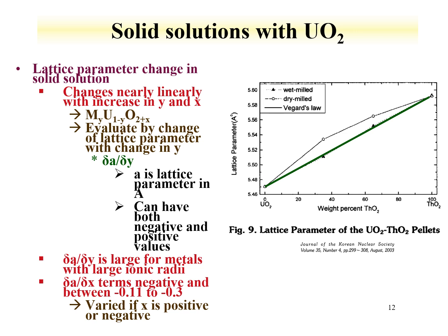So for something that's 50%, the lattice parameter would be a contribution of 50% of the uranium dioxide and 50% of the thorium dioxide. This is a way: if one takes a compound as a solid solution and measures the lattice parameter with X-ray diffraction, you can determine the composition of both. So this linear change is Vegard's law.